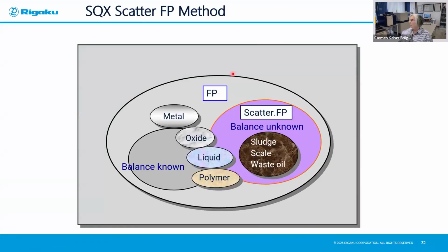So how does it work? This is a pool that you can see of different materials. We have metals and oxides, liquids and polymers, sludges, scales, waste oils. And of course, the semi-quantitative method is using the fundamental parameters method. But if we want to measure these materials, then it is easier to use the scattering FP if we have a very high carbon, hydrogen, oxygen, nitrogen component, which is organic. Therefore, we can measure the balance of these materials very successfully using the Compton line. So it's called a scattering FP method.